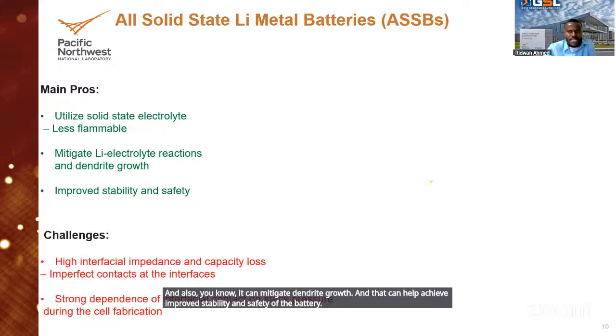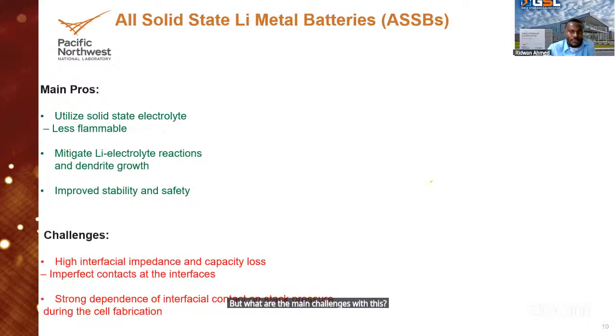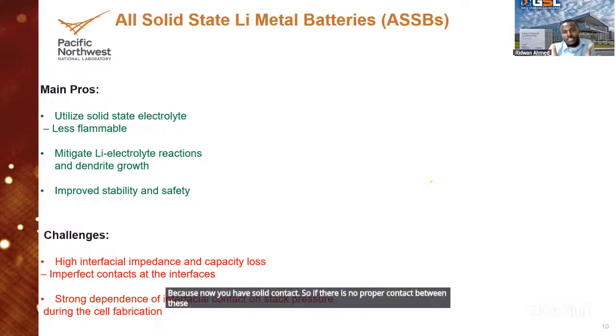But what are the main challenges with this kind of battery? One is high interfacial impedance and capacity loss. Because now you have solid-solid contact. So if there is no proper contact between, let's say, the solid electrode and the solid electrolyte, then the impedance will be high. In other words, the resistance to the lithium ion flow will be very high, which is not good for the battery.